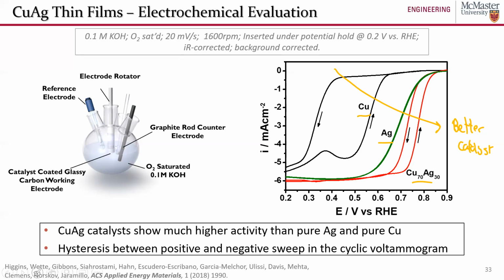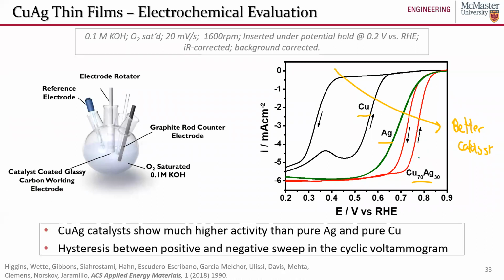We also saw this hysteresis in our polarization chart, where in the upward sweep direction, the activity was better than in the negative potential sweep direction when we were doing our cyclic voltammetry. And so we want to know two things. We want to know, why is copper silver better than pure silver or better than pure copper? We also want to know why this hysteresis was occurring in these CVs.